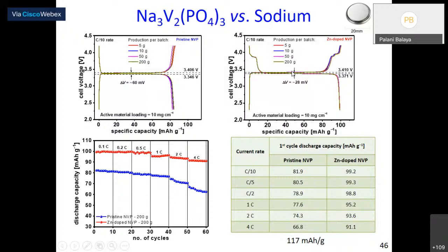But with zinc doping, you can see here, first of all, the capacity has gone up closer to 100. It's written here 100. And then even at 4C, that means 15 minutes charging and 15 minutes discharging, we get a decent capacity of about 91 milliampere hour per gram. So the capacity is improved and the rate performance is also improved. Most importantly, you see here, there is an additional reaction, which is because of vanadium 4 plus to 5 plus. In this case, vanadium goes from 3 plus to 4 plus, and then 4 plus to 5 plus. There is an extra redox reaction, and hence the capacity has gone up as shown here.